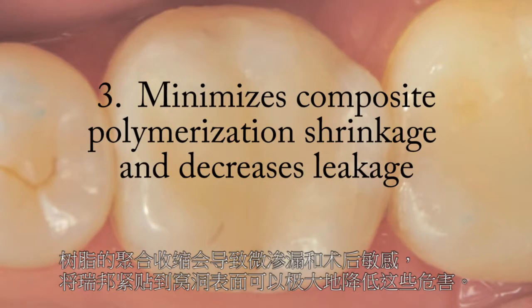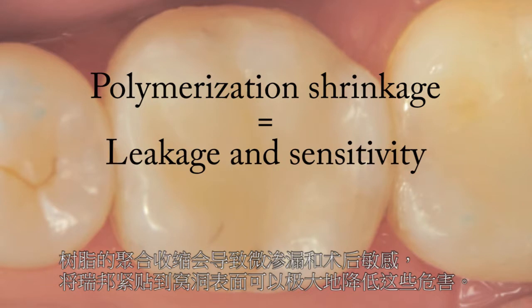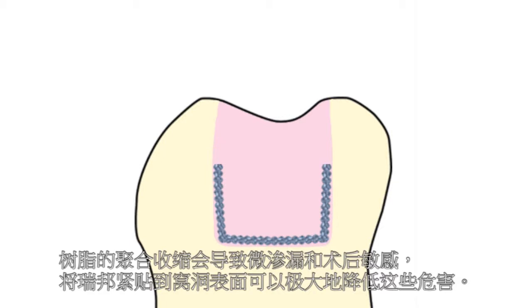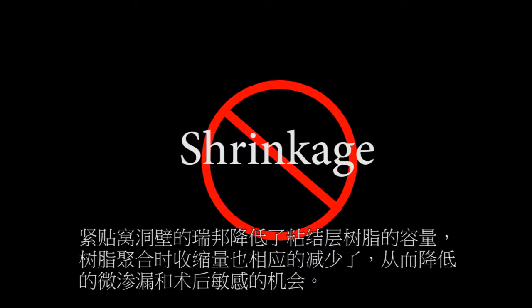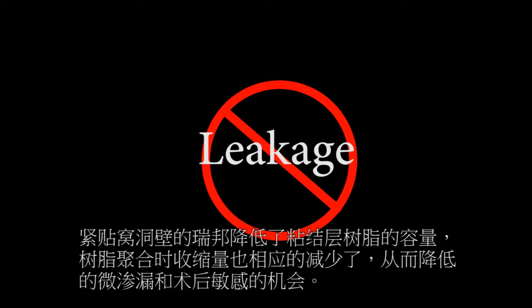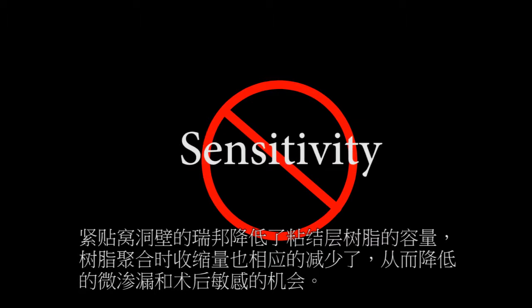Minimizes polymerization shrinkage and decreases leakage. Polymerization shrinkage can result in leakage and sensitivity. Closely lining the preparation with Ribbond significantly reduces and minimizes these harmful effects. Because the Ribbond is closely adapted to the cavity walls, there is less volume of composite to shrink and less polymerization shrinkage, resulting in less leakage and less sensitivity.